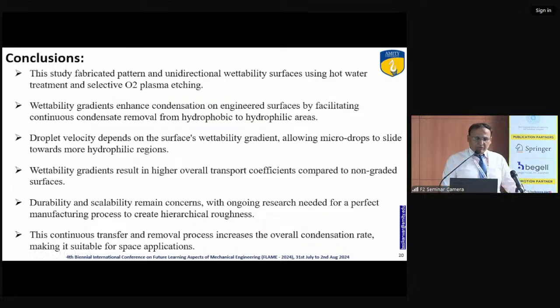So I'm concluding my talk here. This study fabricated a pattern of unidirectional wettability gradient as well as a patterned surface. The wettability gradient enhances the condensation on the engineered surface by facilitating continuous condensation and removal from the hydrophobic surface. Droplet velocity depends on the surface wettability gradient, allowing the micro droplets to slide towards the more hydrophilic surface, and the wettability gradient results in a higher overall transport coefficient compared to a non-graded surface.